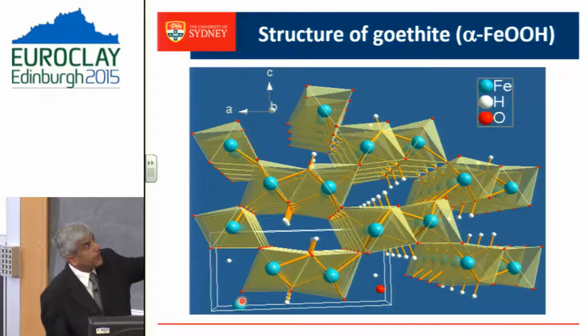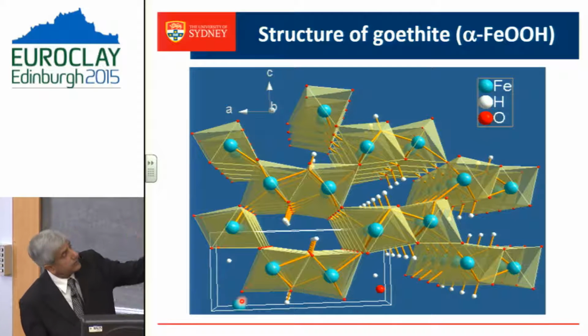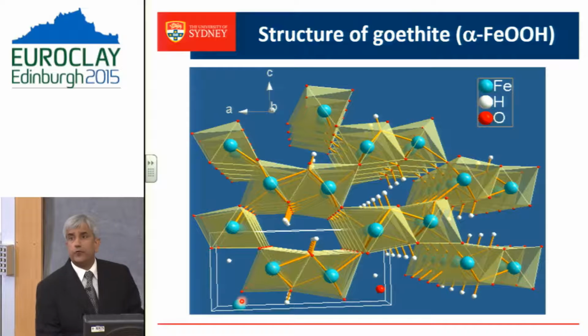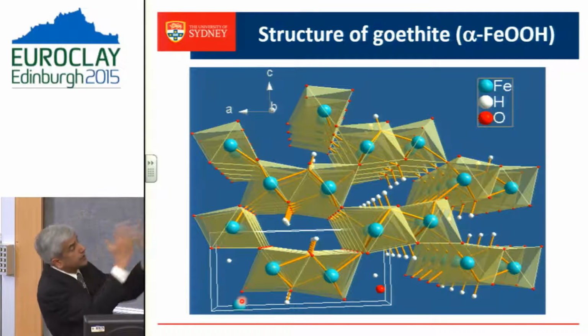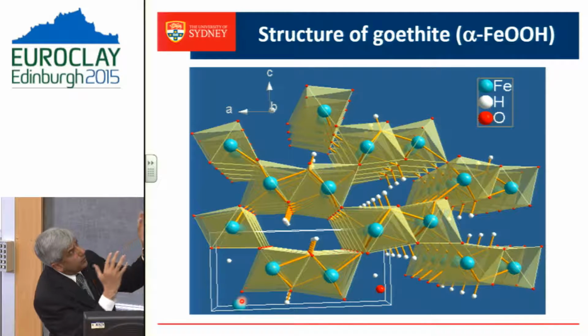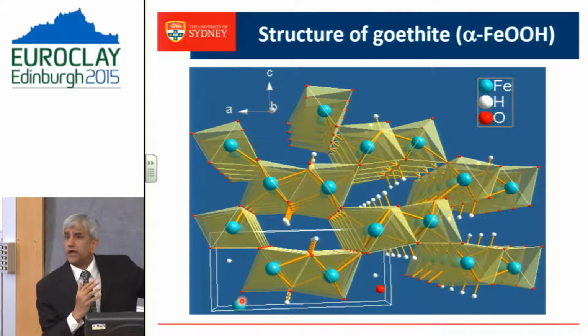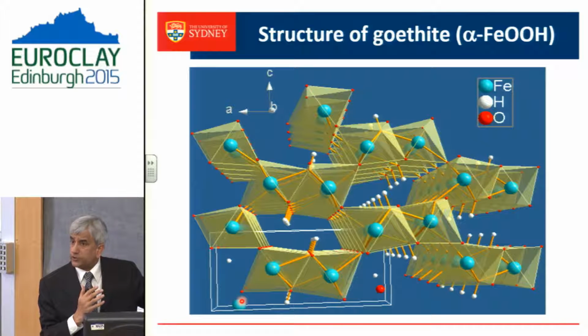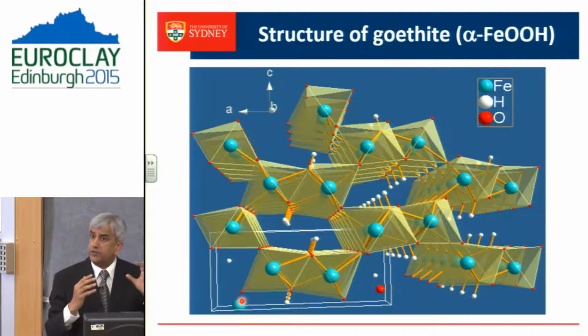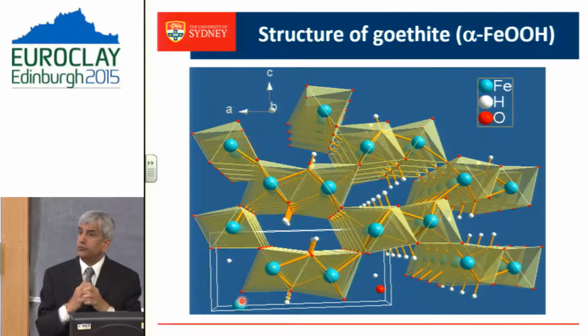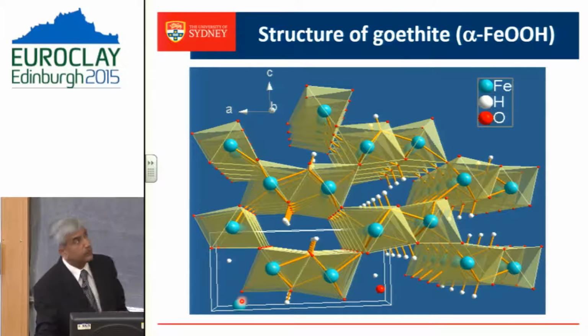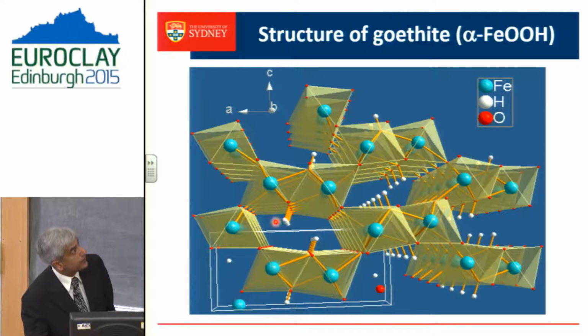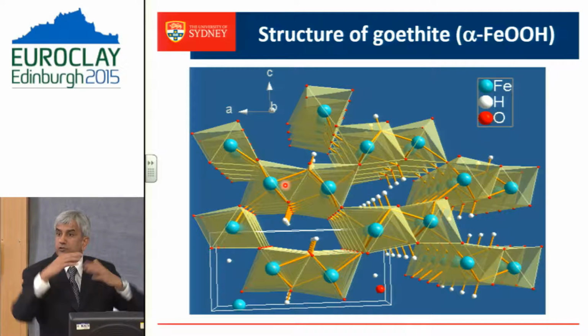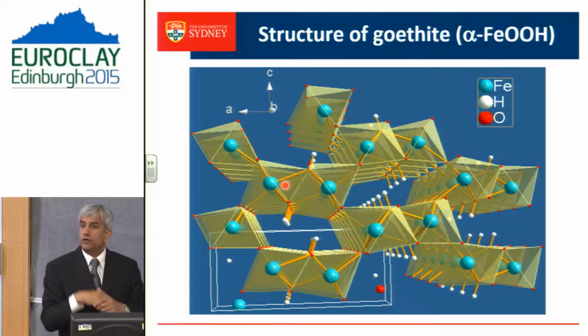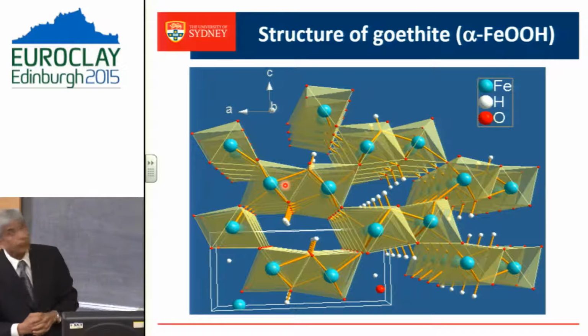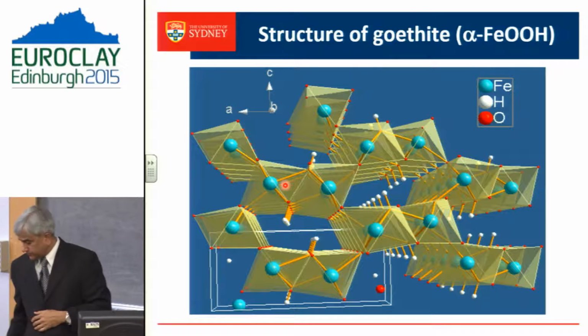Just briefly to remind you of the structure of goethite, it's a kind of parallel chain of double octahedra, and the point to note here is that because of this relatively open structure, there is a lot of capacity for these different cations to get incorporated, because there is a lot of space for these octahedra to stretch, shrink, and distort for the foreign element to get incorporated in the structure.